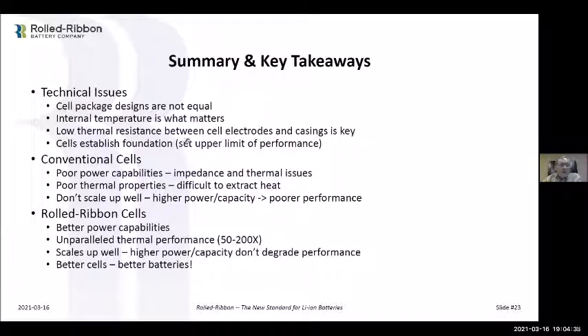Cells establish the foundation, so they set your upper limit of performance. If you got a bad cell, everything you do after that, when you turn it into a battery, is going to make it worse. Batteries never make a cell better; they only make it worse. So you want to start with the best foundation you can get. Conventional cells have poor power capability, again, impedance and thermal issues, high thermal resistance, high impedance, and they don't scale up. It gets worse the more you scale. They have poor thermal properties, and it's very difficult to extract the heat because you can only get it out of that thin strip, that tab. It's the only way you're going to get the heat and the electrons out. So they don't scale up. Higher power and high capacity, you're going to get poorer performance. So it's a given. Physics tells you it's going to happen.